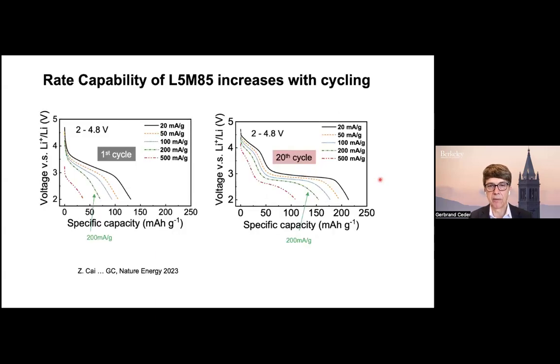So it's interesting, if you look at the voltage profile and the rate capability, there's clearly some change going on. What happens actually is that as this change proceeds in the material with cycling, the rate capability goes up. So this is the discharge rate capability in the first cycle, which is quite poor, right? By the time you're at 200 milliamperes per gram, you've lost half your capacity. But in the 20th cycle, that starts to look much better. Now you can relatively easily get 200 milliamperes per gram in these materials.